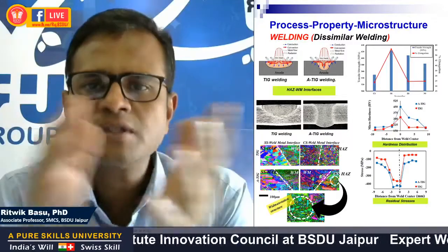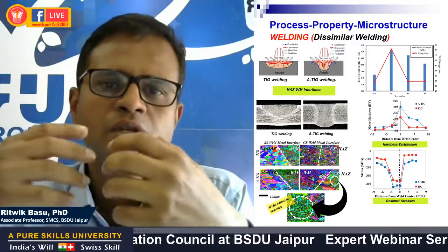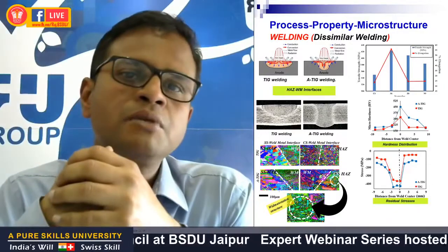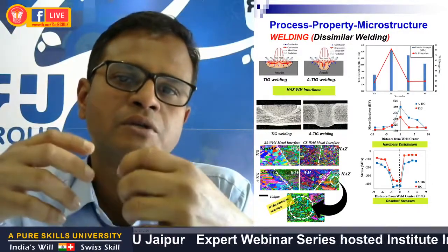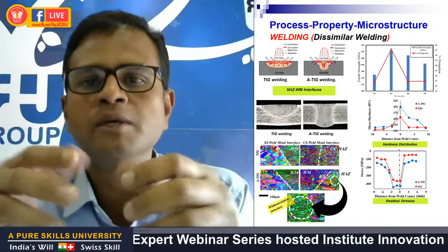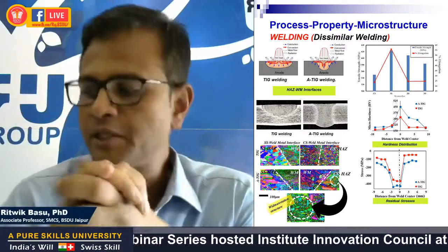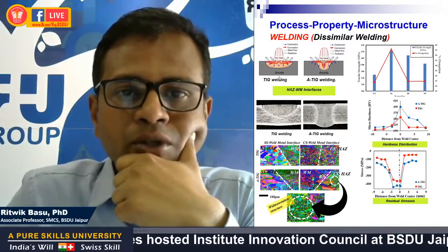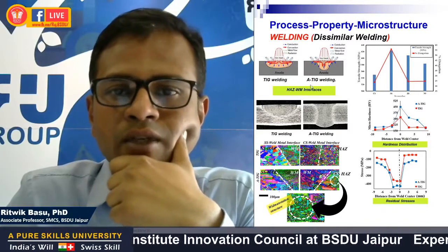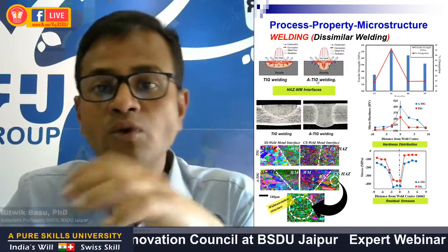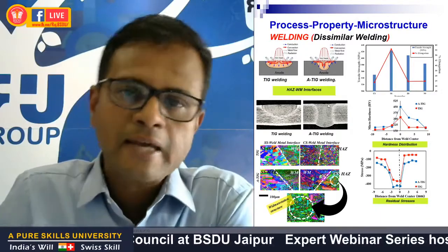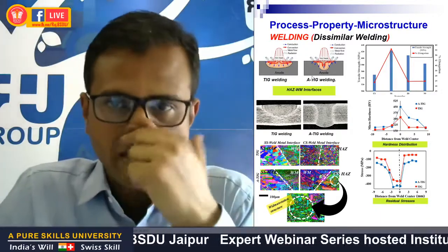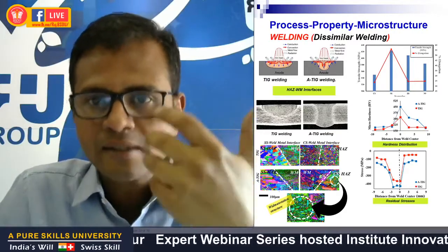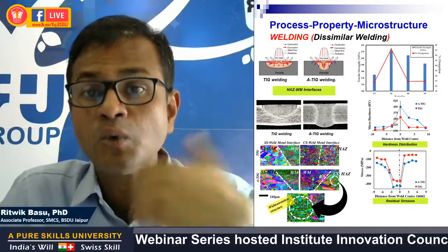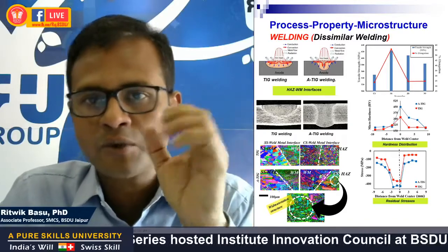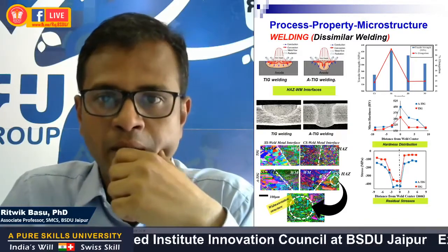Now, these differences in the microstructures, as I was discussing, not only depend on the process variables used, but are also brought about by changing the processes even under identical conditions. So changing the process, for instance, from tungsten inert gas welding to activated tungsten inert gas welding can alter the microstructure significantly, and that can also have a strong influence on the properties of the material. And that is largely because the differences in the cooling rate play a vital role in determining the final microstructure of the weldment.